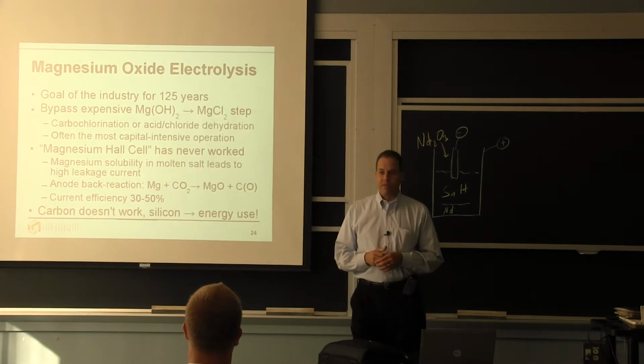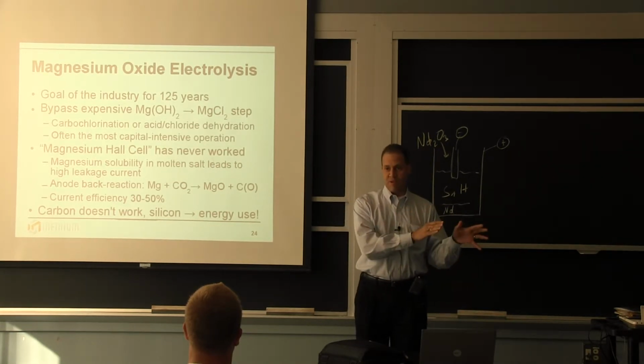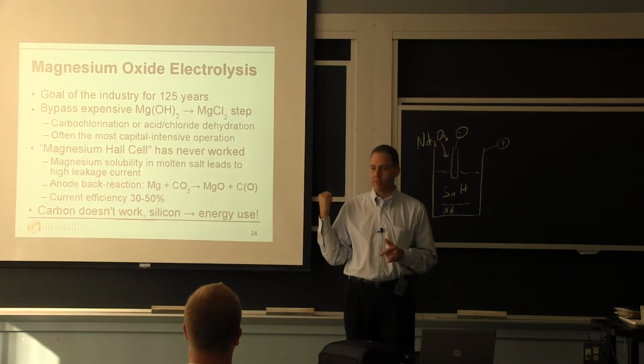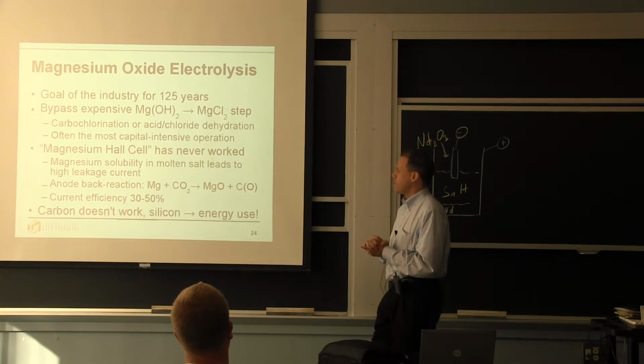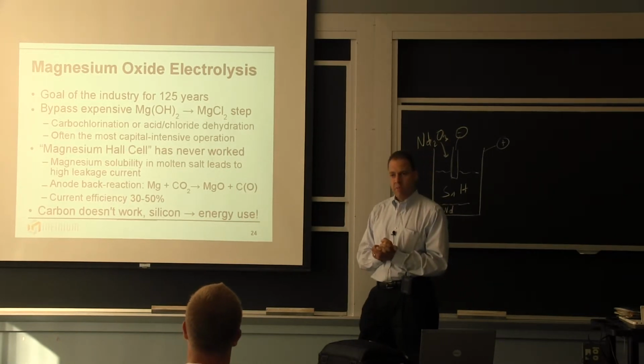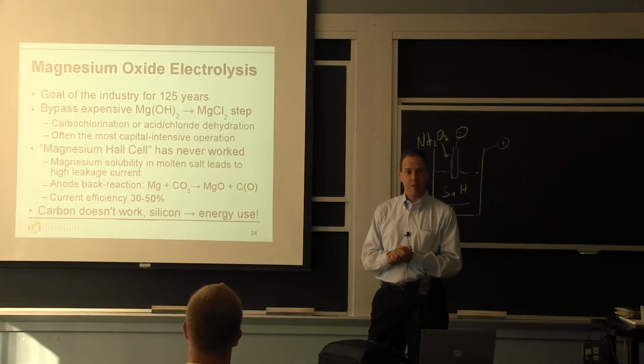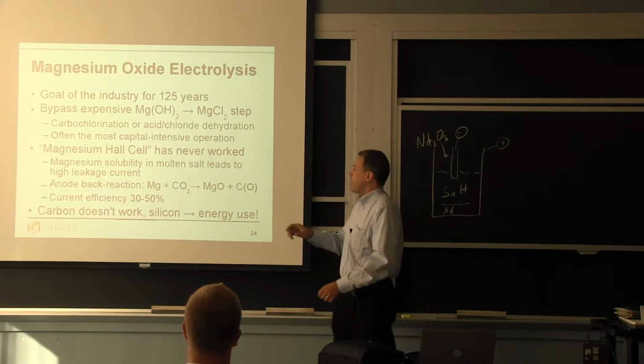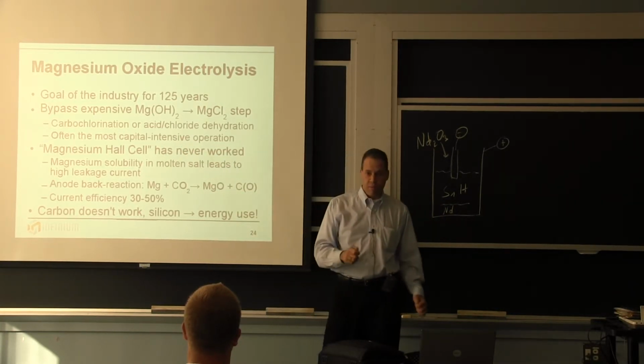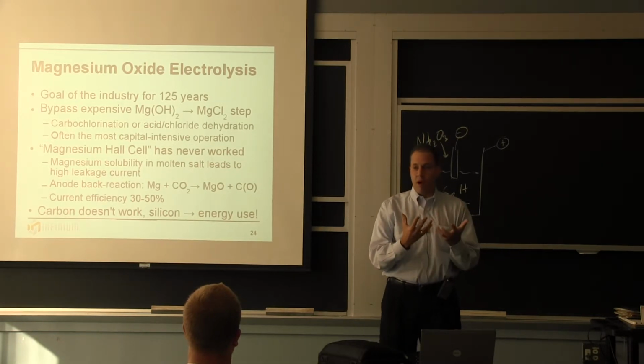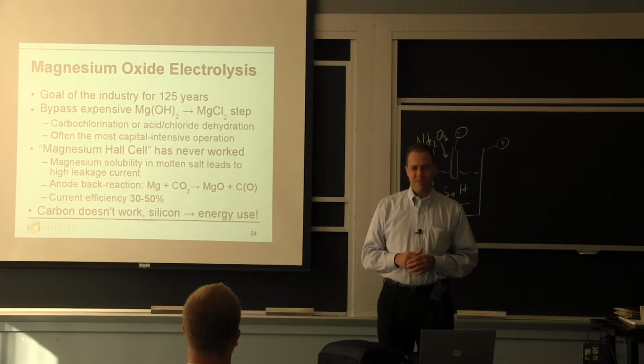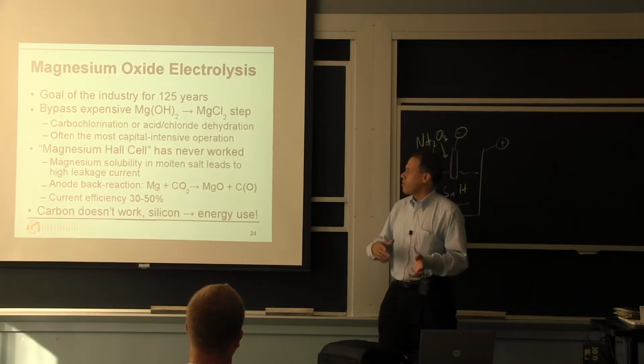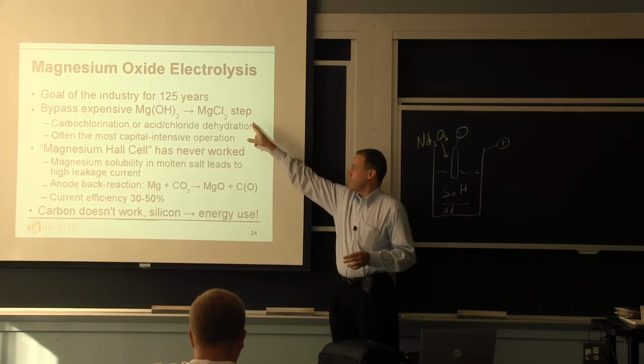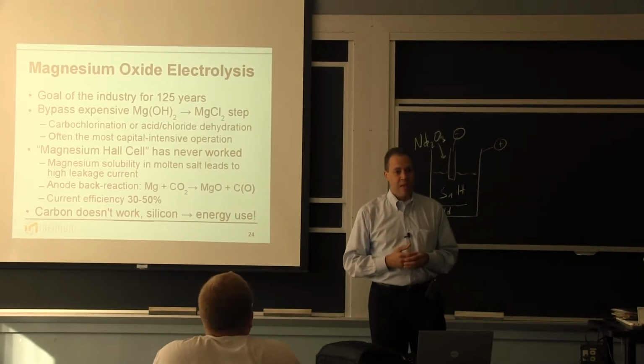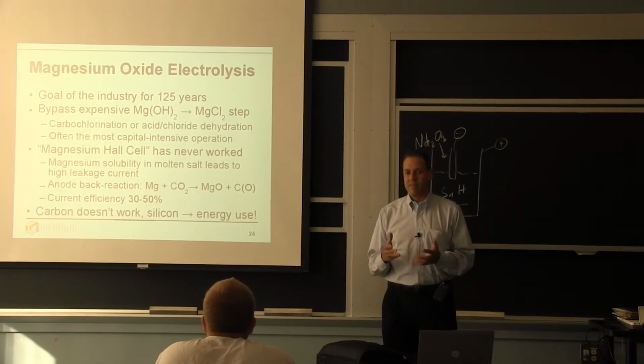Magnesium oxide electrolysis has been a goal of the industry for a very long time, since Charles Hall in the U.S. and Héroult in France showed that it's possible for aluminum oxide. People have been trying to do this, and this is because for both aluminum and magnesium, it's very expensive and very difficult to make anhydrous, high-purity chloride material. You have to do it either by carbochlorination, where you take magnesium oxide plus chlorine in the presence of carbon. It produces CO2 and MgCl2. It also produces dioxins and furans, right? Carbon, oxygen, chlorine. Or you can add hydrochloric acid, and then you have magnesium chloride solution, and then you can dehydrate that. But that's very difficult to do.